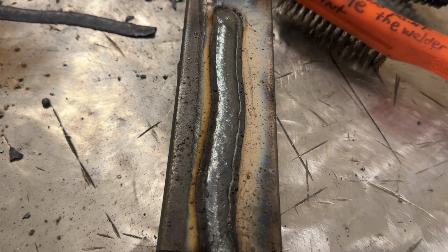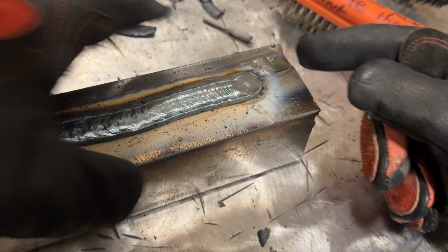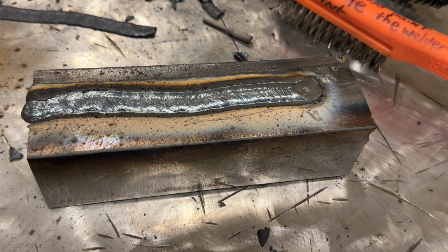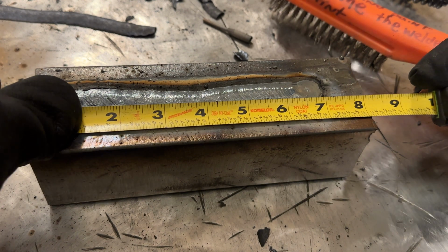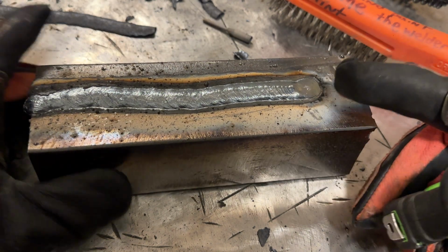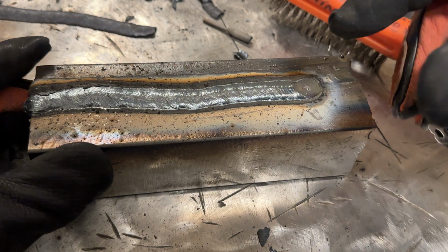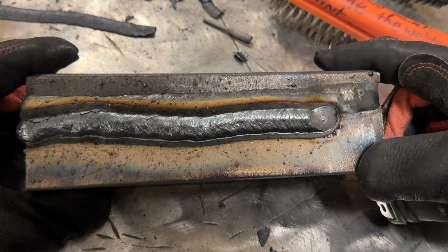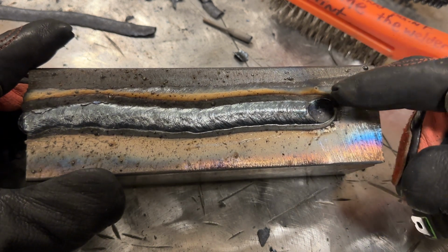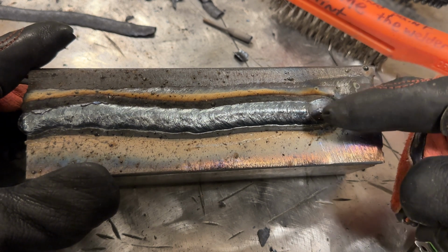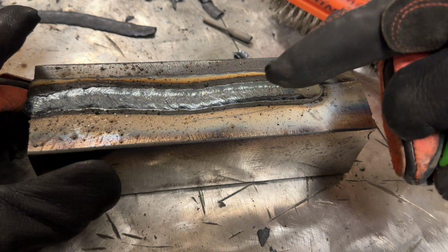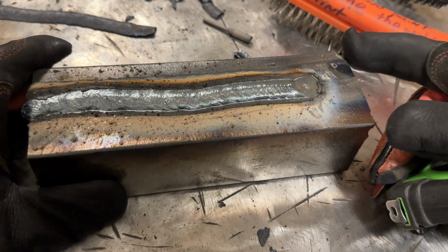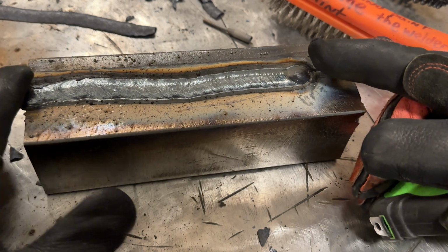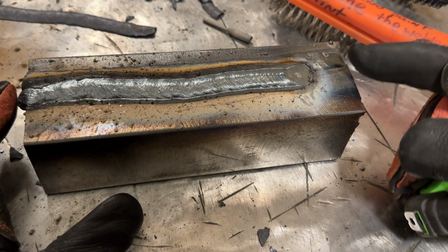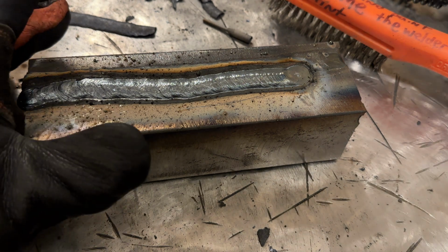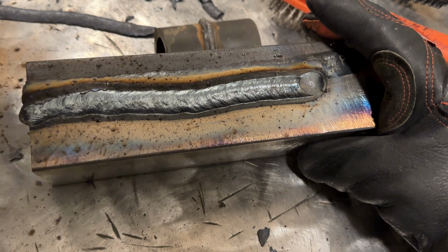So this pass, I slowed down just to show you in a single pass, you can easily do 1/2 inch wide on this, but a single rod did not make it the whole length. And just to give you an idea, I'm not sure how long this is. So this is about 8 1/4. So the slower your travel speed and the more rod you push in there, the wider the weld gets and the more metal you deposit. So my first pass, which granted it was on a cold plate, deposited, I would say, about 1/3 less metal, but by slowing down your travel speed and feeding more rod in, you can really make a real wide, big weld, but at the expense that one rod only made it to there versus a previous pass I made it to the end.